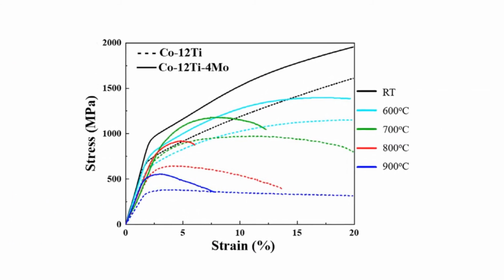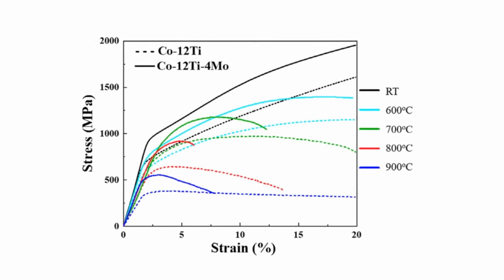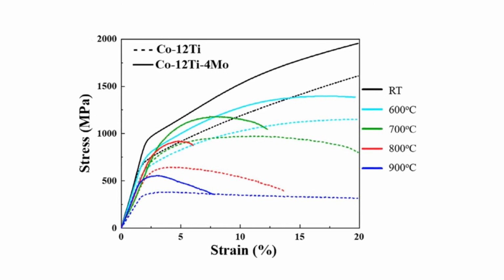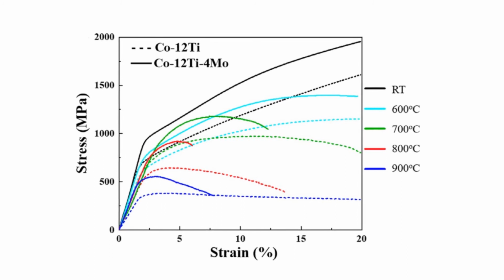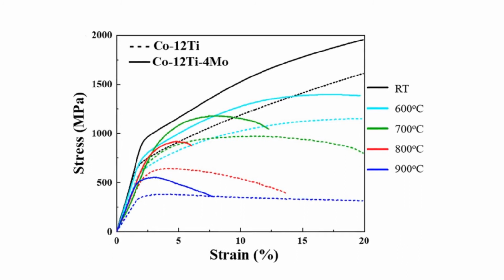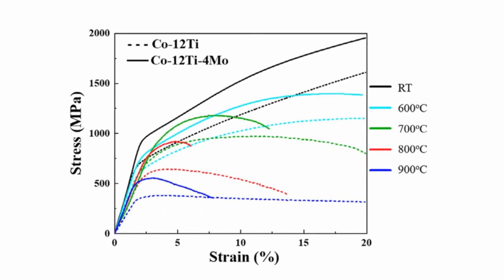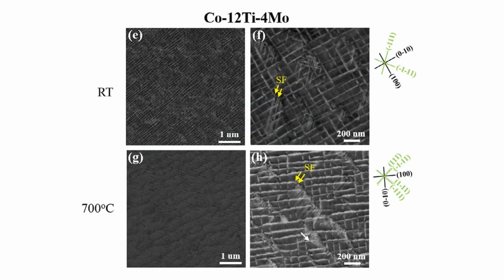In this context, we investigated in our recent paper the flow behavior of gamma, gamma-prime strengthened cobalt alloys with 12% titanium and cobalt alloys with 12% titanium plus 4% molybdenum, at room temperature and at elevated temperatures up to 900 degrees Celsius, by electron microscopy and density functional theory.